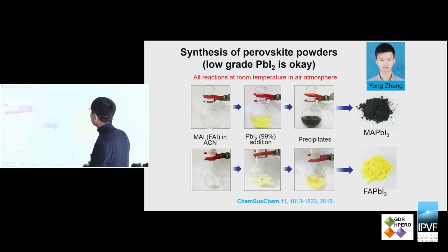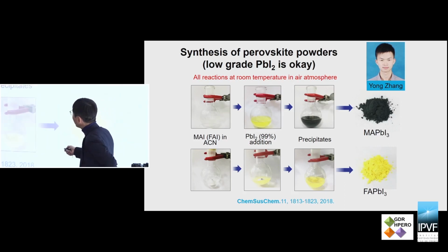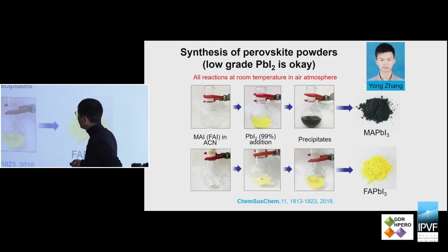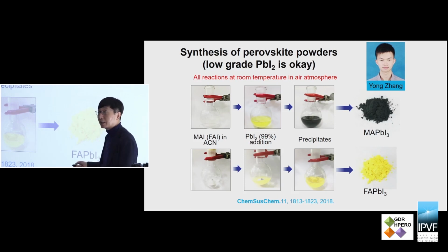a process that requires little energy, at room temperature. All the reactions were done at room temperature in air atmosphere, without using a nitrogen or argon atmosphere. So for instance, the precursor material MAI or FAI is first dissolved in acetonitrile at room temperature, and then the low-grade PbI2 powder is added to this solution, and by stirring for some time, there is some precipitation. For MAPbI3 it is a black powder. This is a perovskite phase.